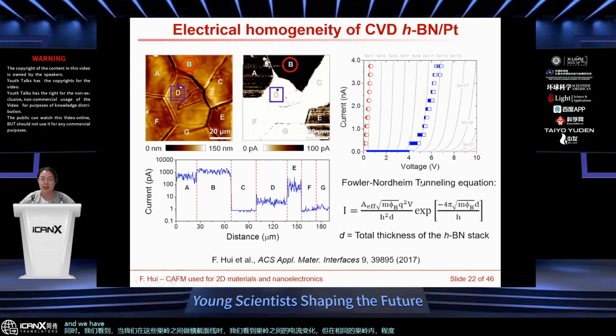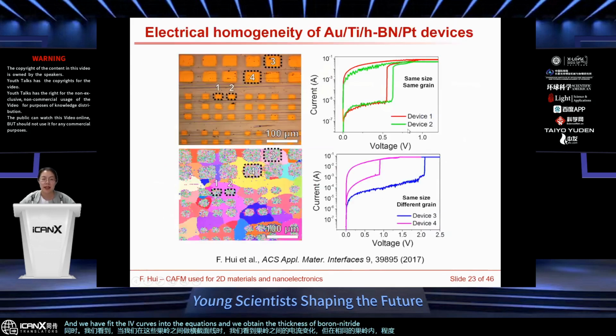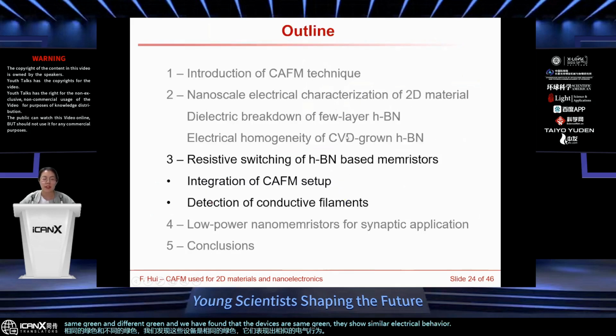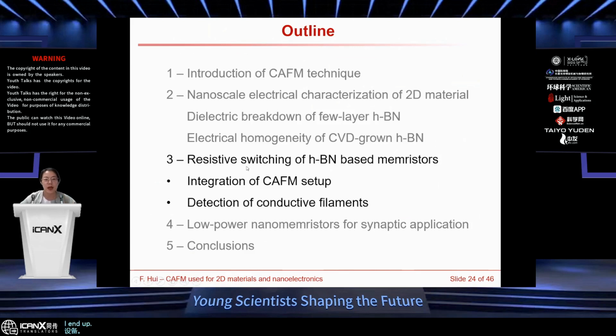We fit the IV curves to equations, and obtained a thickness of boron nitride ranging from monolayer to 13 layers. This has been further demonstrated at the device level. We characterized devices on the same grain and on different grains, and we found that devices on the same grain show similar electrical behavior, and vice versa. So it's important to get uniform thickness of two-dimensional materials for electrical devices. In the third section, I will introduce the study of resistive switching of hexagonal boron nitride-based memristors.